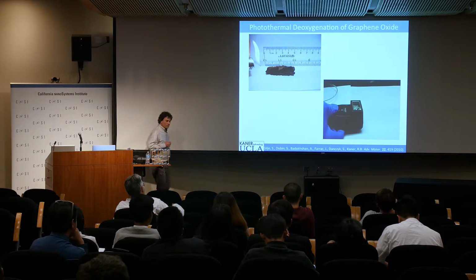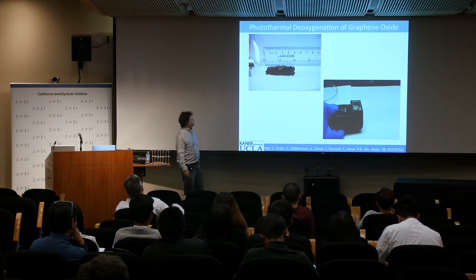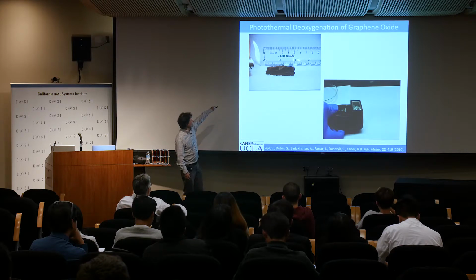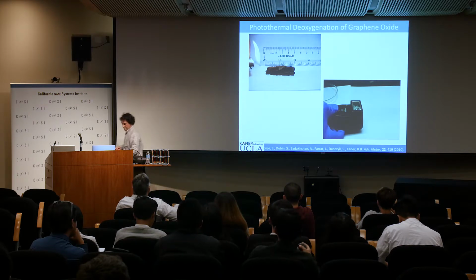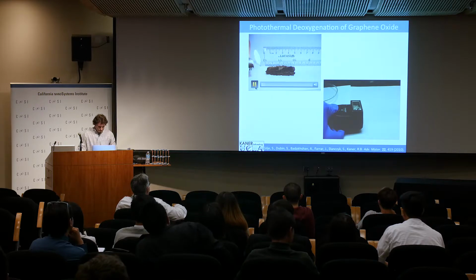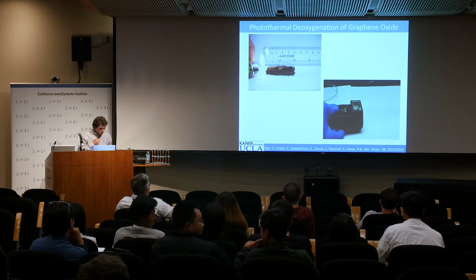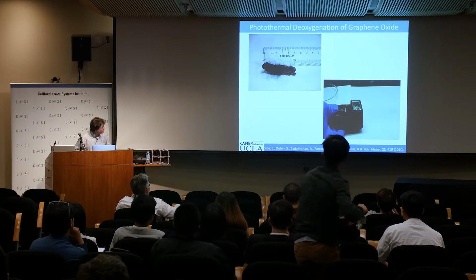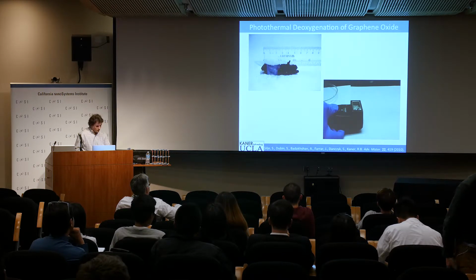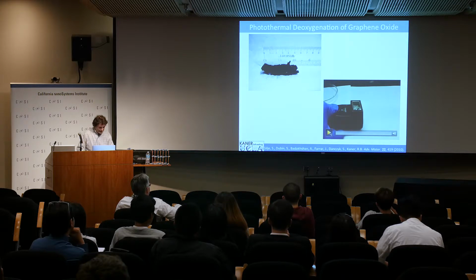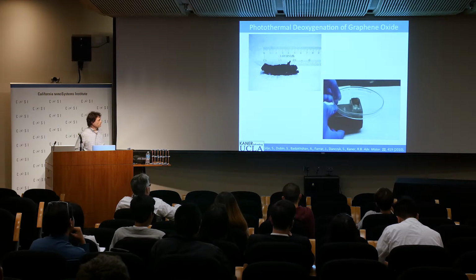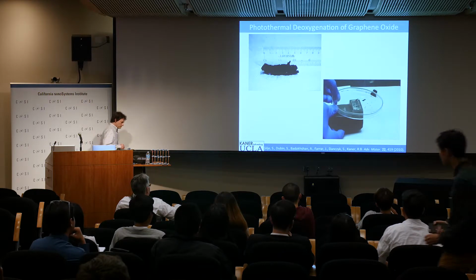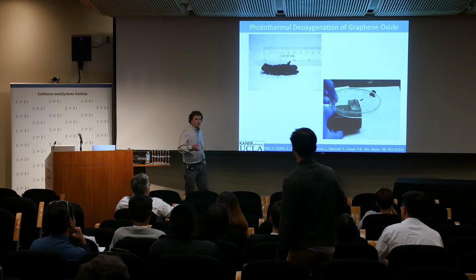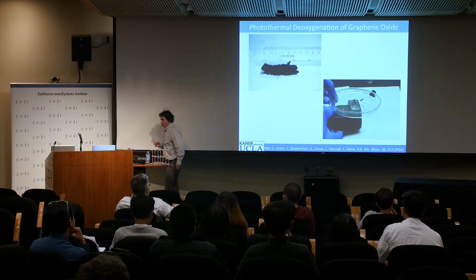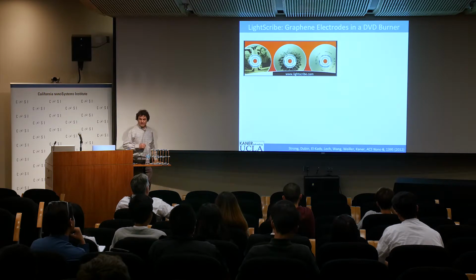But what I want to show you here is something called graphene foam. So what we did is we freeze-dried the stuff. It has this nice golden color. And I'm just going to light this on fire. What's interesting, it's not quite burning up. It looks like something's happening. And now we're going to take graphene oxide paper and hit it with a camera flash. Okay, so these are two very uncontrolled reactions. But imagine controlling this. And one way to do that is using LightScribe.